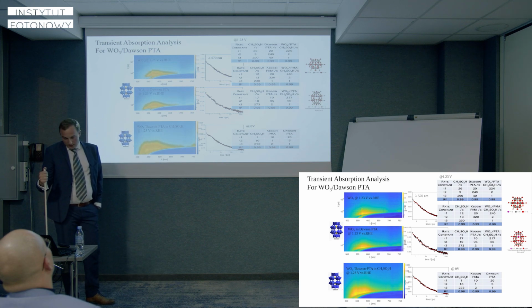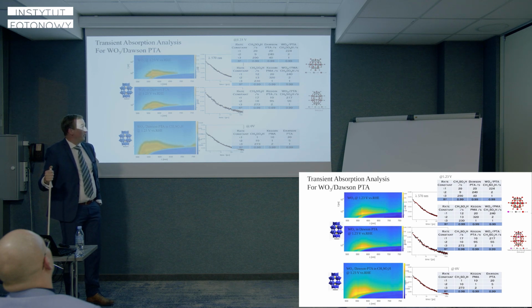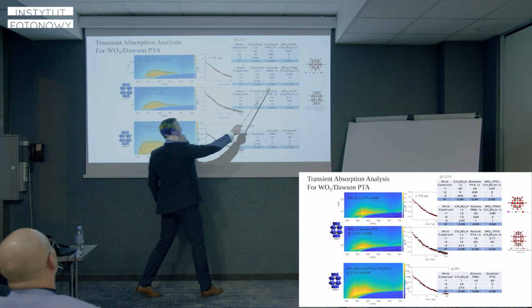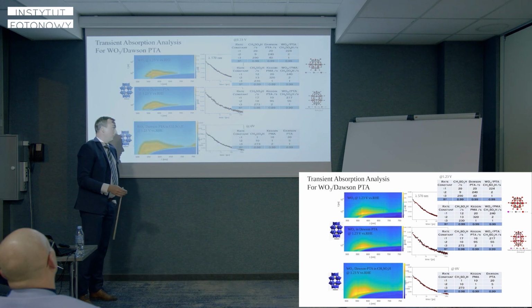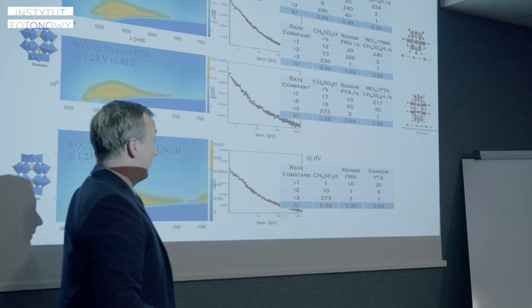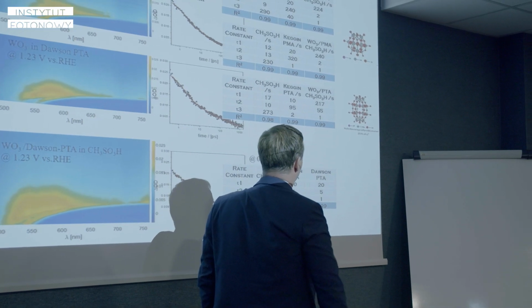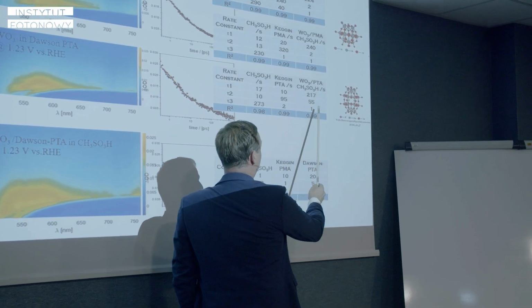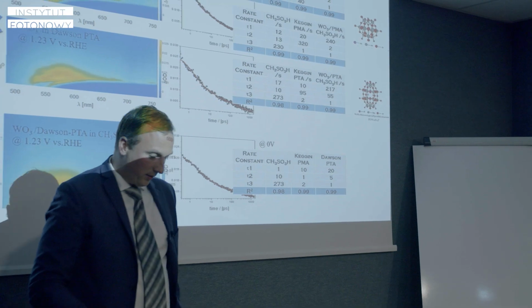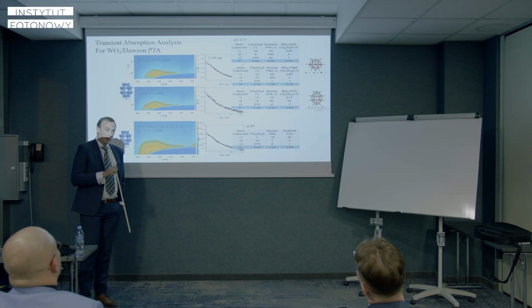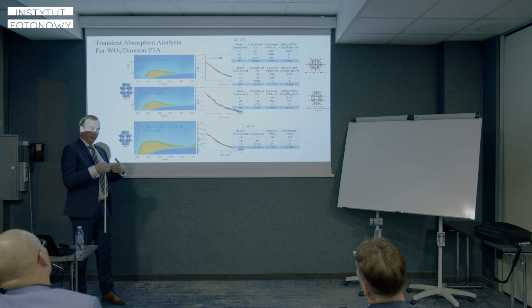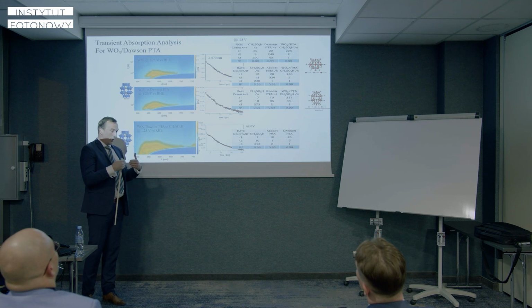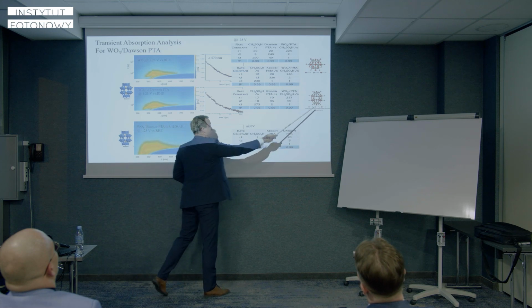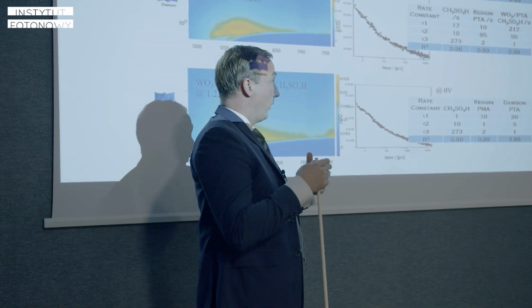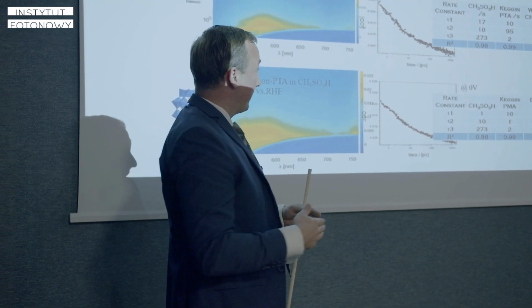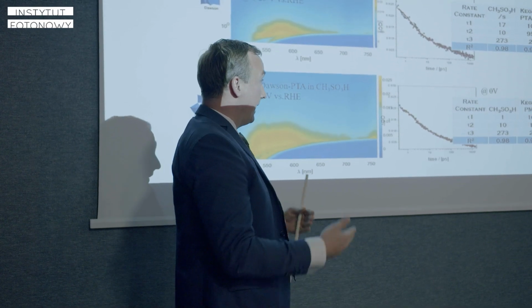All POMs, when present in the electrolyte, increased the second time constant, and this is the same situation for all these polyoxometalates. But when we compare the situation after removing the polyoxometalates from the electrolyte, we can notice a very interesting thing, because the Dawson type polyoxometalate still increases the second time constant. So it means that there is still a change in the depletion region because of this non-spherical polyoxometalate. So we think that this polyoxometalate works as a plasmonic structure and causes an evanescent electric field.